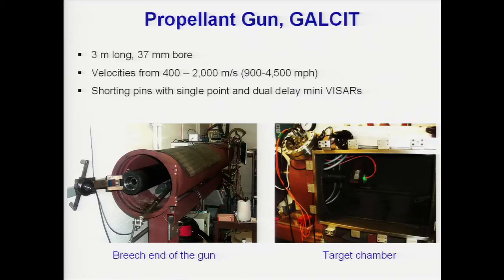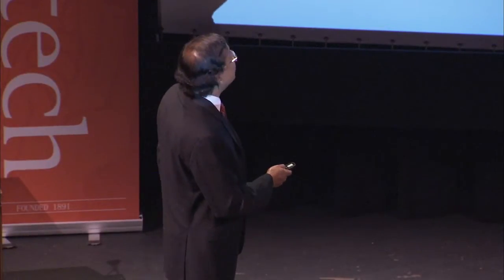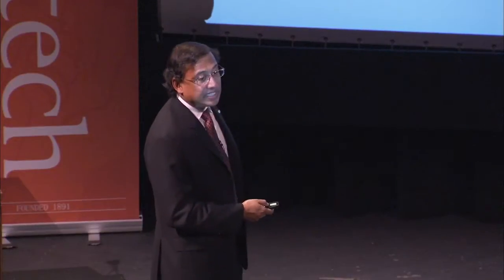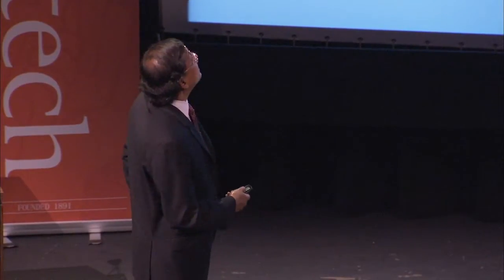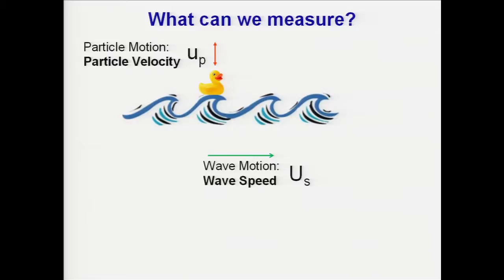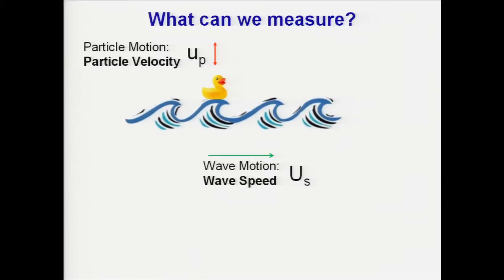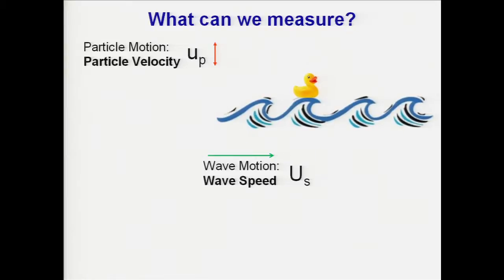This impact is occurring in the range of 400 meters to 2,000 meters per second. So we can go up to about 5,000 miles per hour. So what can we measure in the lab? We can measure two things. One is the particle velocity. For example, this duck is sitting on this wave, and if the duck is moving up and down as the wave is moving around, we can measure that. And as the wave is moving about, we can also measure the wave motion. So we can measure essentially the wave speed and the particle velocity.